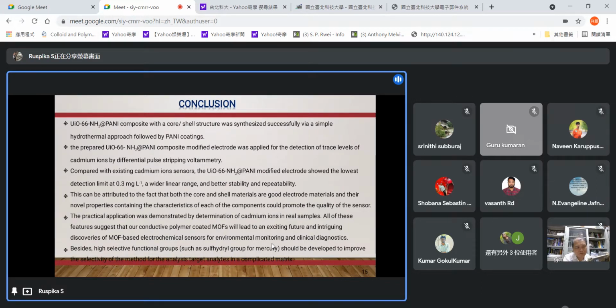and the prepared composite modified electrode is applied for the detection of cadmium ions by DPV, and compared with other cadmium ion sensors, it shows a lower LOD at 0.3, with a wider linear range and better stability and reproducibility. The practical application was demonstrated by the determination of cadmium ions in real samples. All of these features suggest that our conducting material coated MOF will lead to an exciting future and intriguing discoveries of MOF based electrochemical sensors for environmental monitoring and clinical diagnosis.